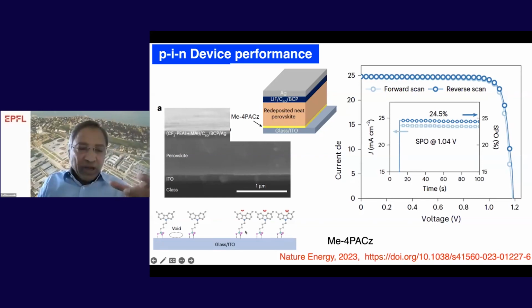What you do is you have a hole transporting group, a head group, and an anchoring group. You mix this 4PACz or 2PACz hole transporting self-assembled monolayer in the perovskite solution. When you deposit on top of ITO, the self-assembled monolayers are attracted to the ITO and form a monolayer of the hole transporting material. Then this monolayer guides the perovskite crystal growth on top of it, followed by C60, BCP and silver as contact layers.